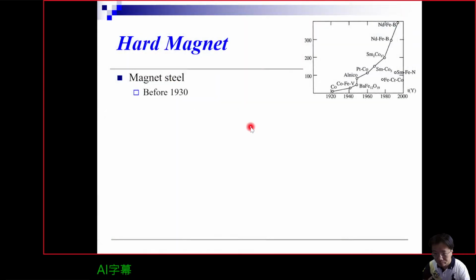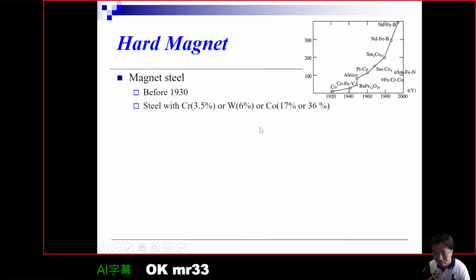Okay, I just lost my control a little bit for a while. So let's introduce the whole history of this hard magnet. Before the 1930s, we used magnetic steels. That is steel with 3.5% chromium and 6% tungsten, and cobalt at 17 or 36% in the steel. So we can make a magnet steel, and its coercivity is about 250 Oersted.